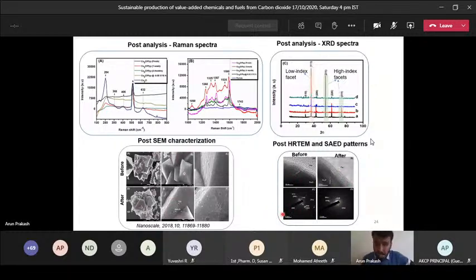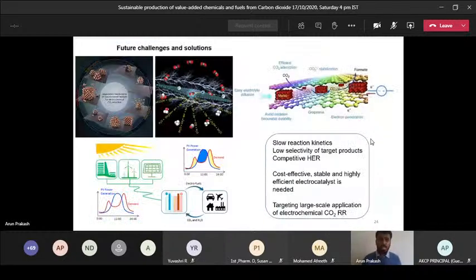And finally, what are the future challenges and solutions? Whoever works on CO2 reduction, or plans to work on it, has to think ahead about what goals they need to achieve. There are several challenges in CO2 reduction. The degradation mechanism of copper-based catalysts is a huge issue. The catalyst can degrade, dissolution can happen, the catalyst may reshape, Ostwald ripening will happen, and also fragmentation. Fragmentation means breaking, and the broken fragments can agglomerate again. So this is an issue. You have to monitor all these processes to improve the stability of your catalyst.